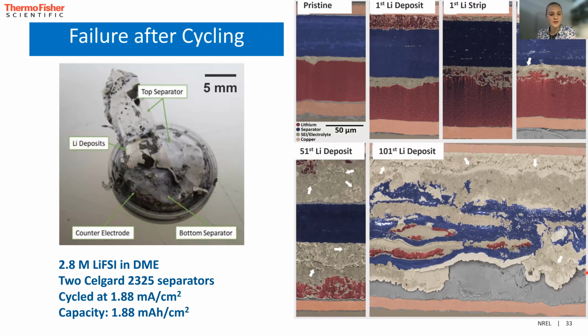Okay, so our first paper was just showing the ability of this tool. What we did was we compared what happens to a coin cell, and this is 2.8 molar lithium FSI and DME with 2 Celgard 2325 separators, cycled at a fairly high rate. And so the pristine cell, the separator we false colored to be this blue, and then the lithium's in red, and then the copper for the current collector.